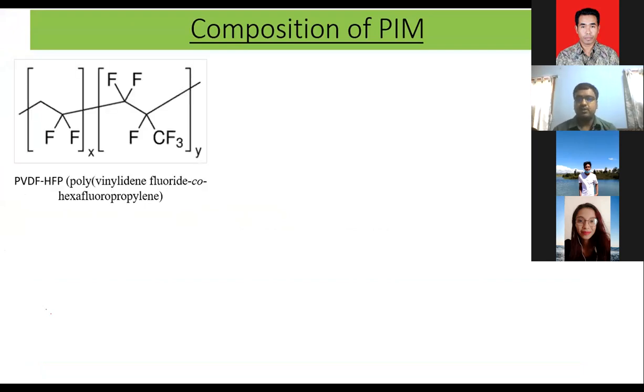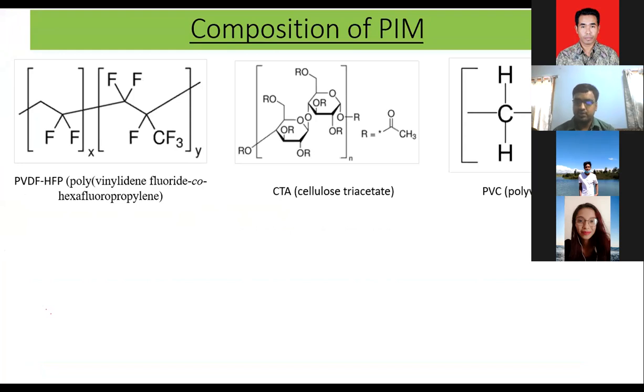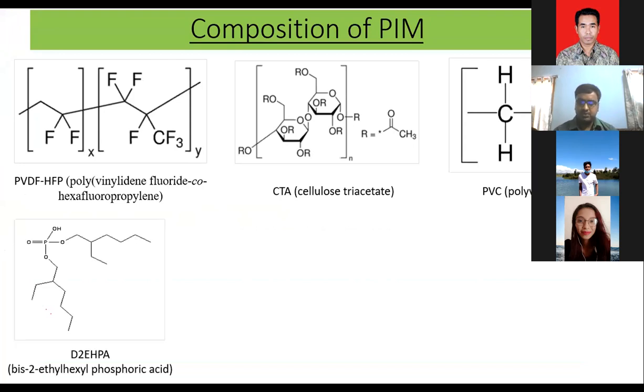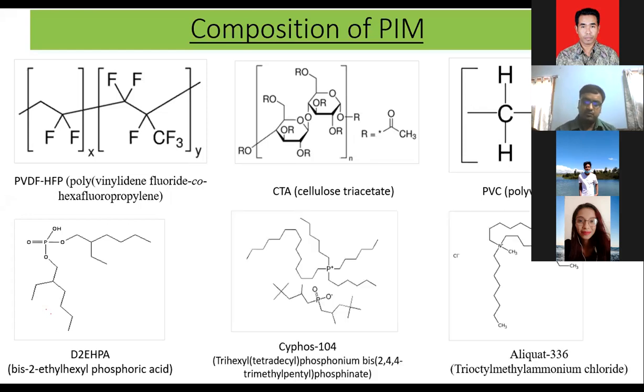In my study, we have used three different base polymers. As you heard from the previous talk, the polymer inclusion membrane is composed of a base polymer and an extractant. These are the three base polymers that we used in my study: PVDF-HFP, CTA, and PVC. We mixed them with different extractants one at a time. Fidel used D2EHPA for zinc extraction. I used Cyphos 104 and Aliquat 336. In my study, I used Cyphos 104 for the gold recovery.